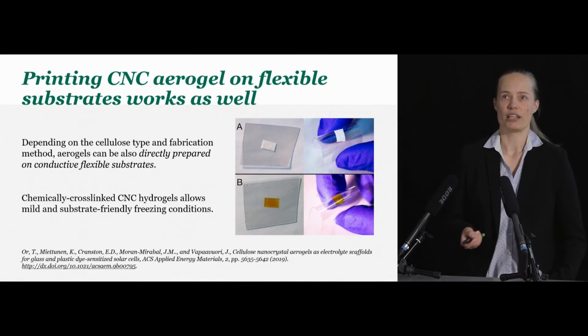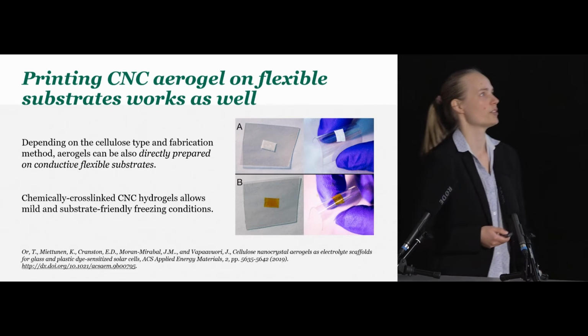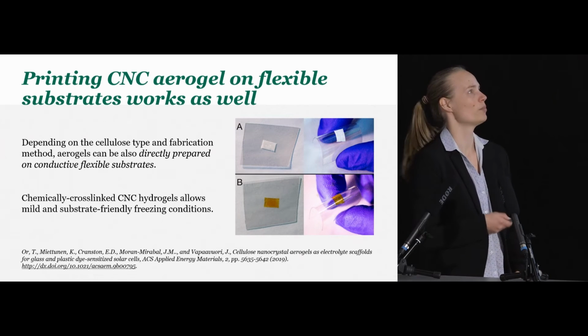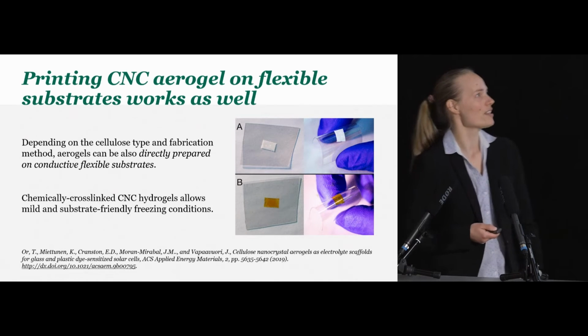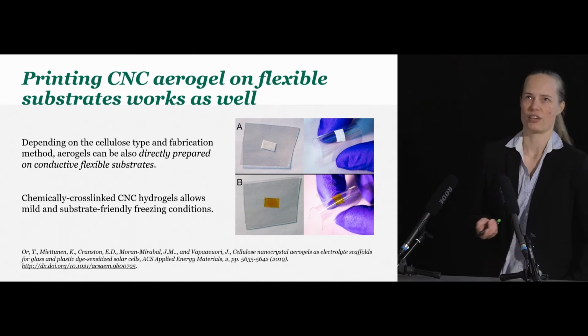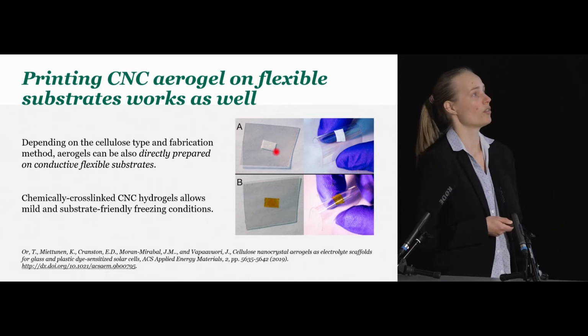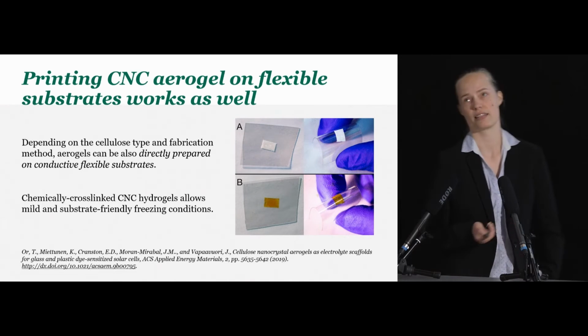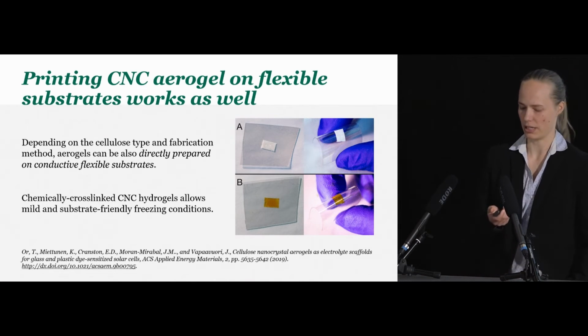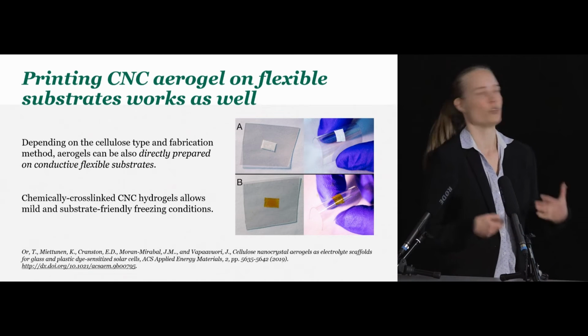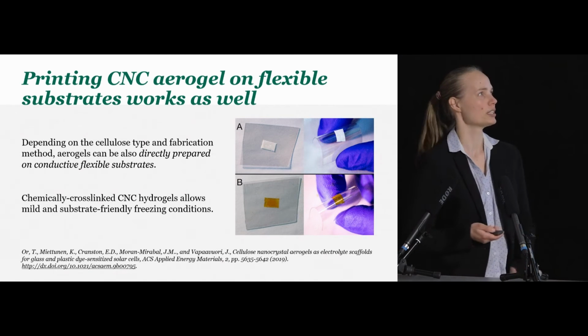And a great advantage, again, was that this same strategy of using cellulose nanofibril printed cryogel type of thingies can also be applied on a flexible conductive substrate, as is done here on a typical ITO PET substrate, and then you could build flexible solar cells based on this.